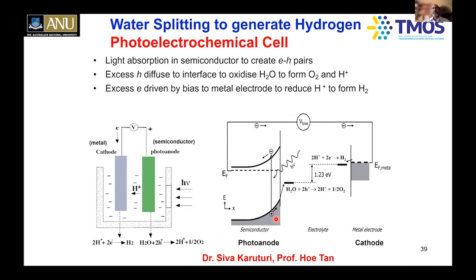So we're also using these nanowires for hydrogen generation. As you know, solar cells are very good for generation of electricity during the sun time when the sun is there. But then afterwards, you really need to charge some batteries or so. Whereas hydrogen is seen as a transportable and storable energy, and that's what we are making use of, using something called photoelectrochemistry or photocatalysis. In this case, we take a photoanode, which is a semiconductor, and a photocathode, which is a metal. And so what you do is shine light on top of the photoanode. And then what you do in this case is generate electron hole pairs. Holes come and oxidize water to generate protons here. Electrons go there and then combine with the protons to generate hydrogen here, for example. So really a simple process.